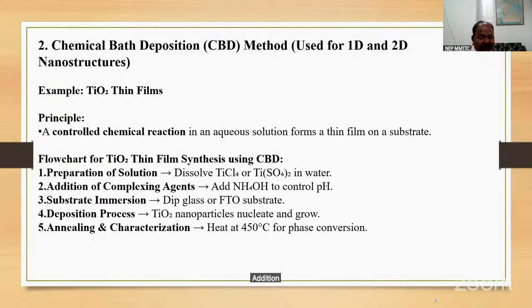Addition of complexing agent. Add NH4OH, ammonium hydroxide, to control pH. Substrate immersion: now dip the glass or FTO substrate. During this deposition process, titanium oxide nanoparticles nucleate and grow. Annealing and characterization: heat at 450 degrees Celsius for phase conversion.